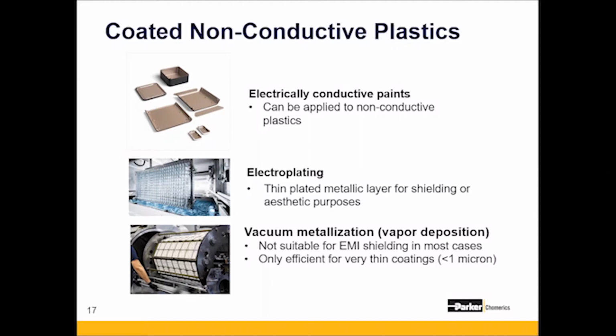Basically, if you try to vacuum metallize a super thick coating, you'll take the plastic to the threshold of melting. So the way that people get EMI shielding out of vacuum metallization is they give it a dose of metal particles, let the part cool down for a while, then give it another dose. Sometimes that could take 2 or 3 applications to get to the thickness required for EMI shielding. So that's why we say, even though the process itself will get you there, it's just not an economical way to get there for EMI.